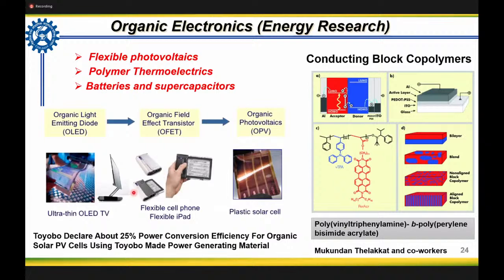That is not known, but a lot of work has been done in tuning the band gaps and synthesizing new materials to tune the band gap. Several aspects have been taken care of. But in most cases, again, the morphology of the donor and acceptor molecules, how we organize them, basically determines the efficiency of these materials. The ideal morphologies are those shown in this cartoon. You can see red and blue polymers here. If we can have morphologies of donor and acceptor molecules like this, where the domain size or periodicity is 10 to 20 nanometers, which matches the exciton diffusion length, then we can get better efficiencies.